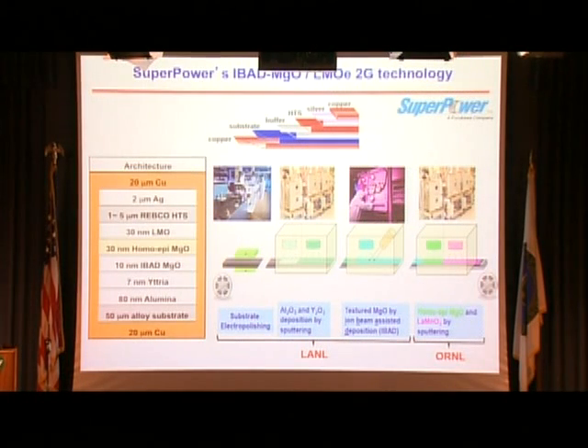So, as I mentioned to you previously, Los Alamos National Lab has been instrumental in taking the work from Fujikura and Stanford and taking it to a point where it could actually be commercialized. And they developed these areas in a roll-to-roll configuration. And this layer, the critical layer, the ion beam assisted deposition layer, basically you have an ion beam coming in, which prevents atoms from any other configuration but one to deposit on a surface, and hence you get a single crystal-like layer.